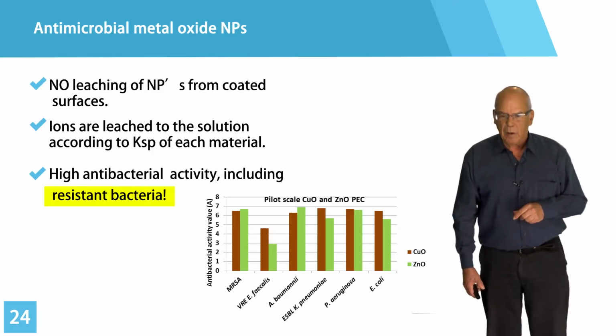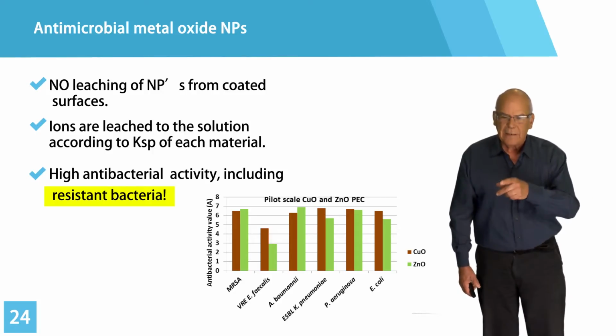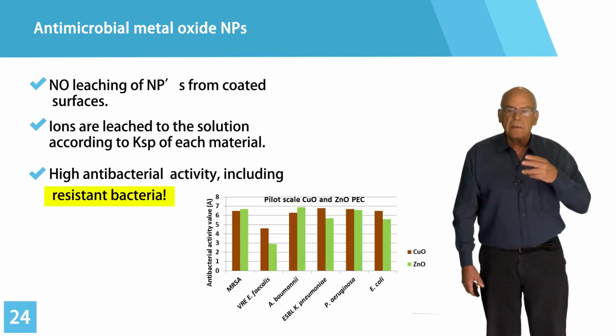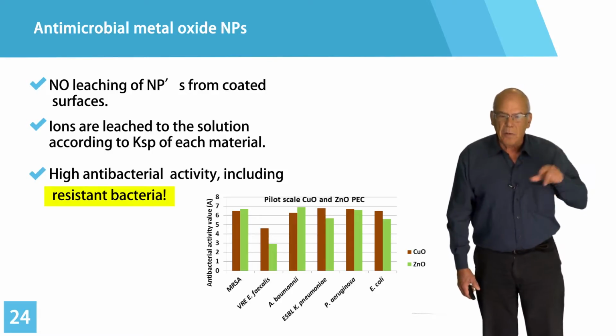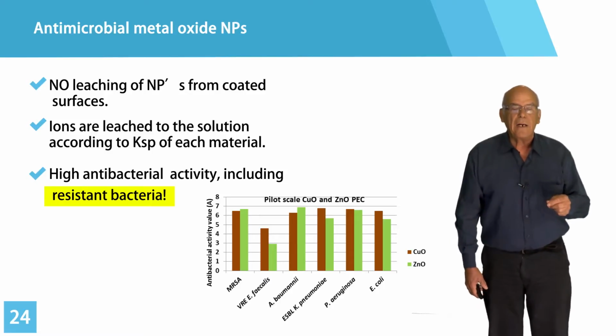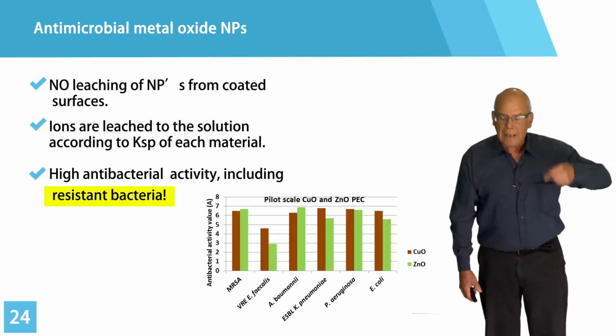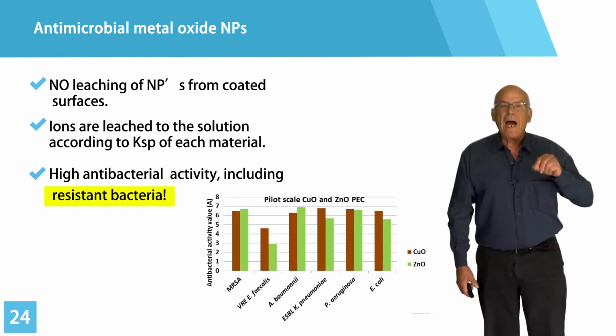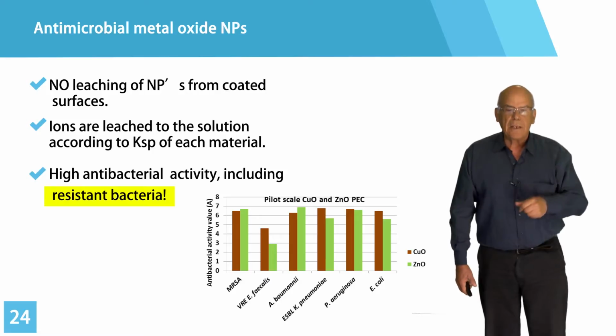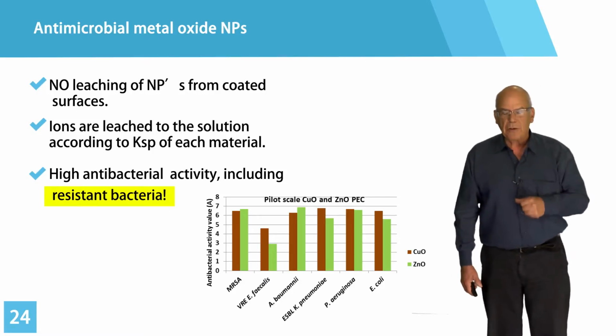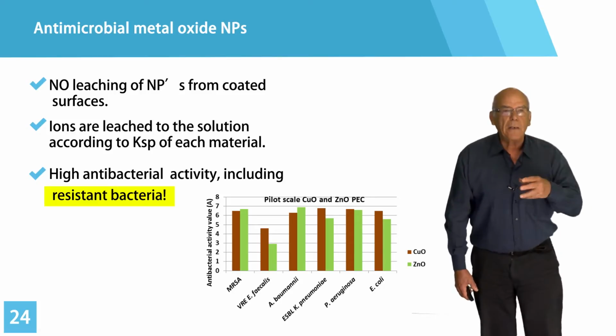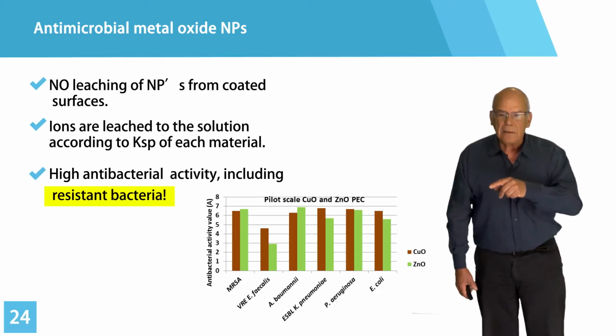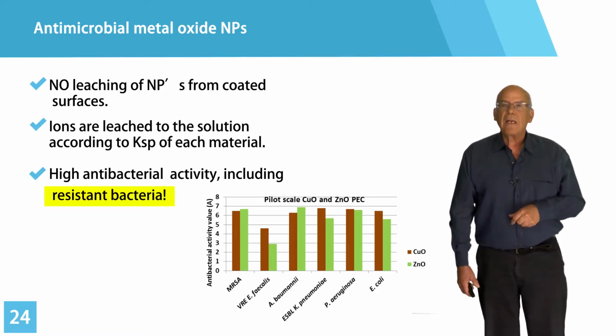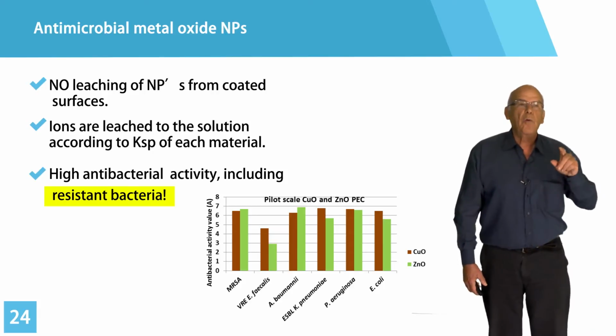And in this slide, you see 1, 2, 3, 4, 5, 6 different resistant bacteria that were killed by copper oxide or zinc oxide, which means that the probability that the new material will do the job is even higher, because it shows, and through the mechanisms that we are familiar with, they are very promising to do a better job related to resistant bacteria. What is important is what is mentioned here in the slide, that once we deposit it on a surface, this mixed or pure metal oxide, when we deposit them, there is no leaching.